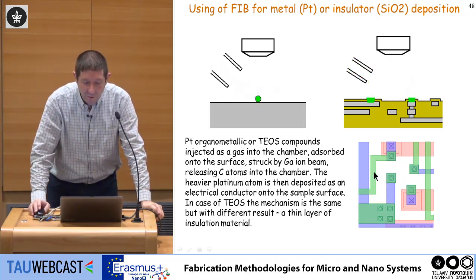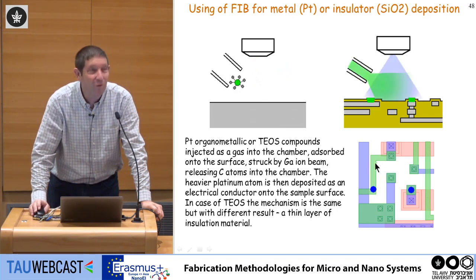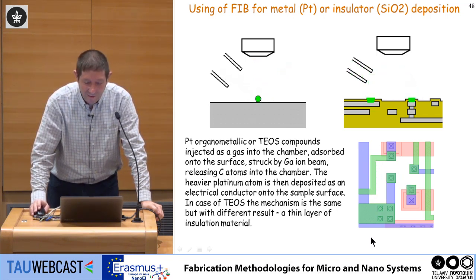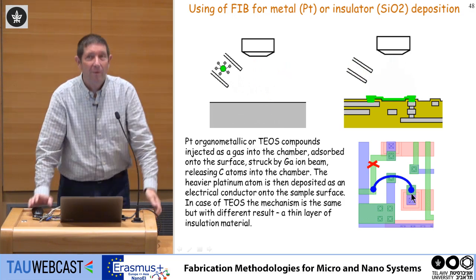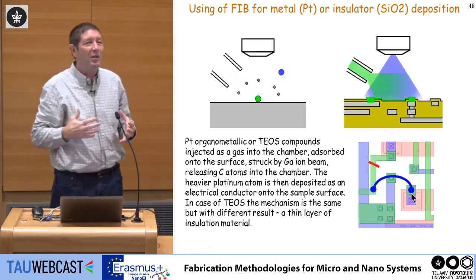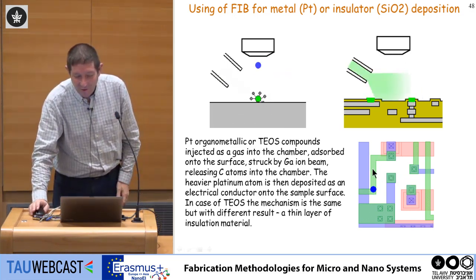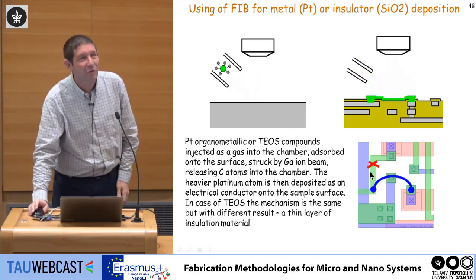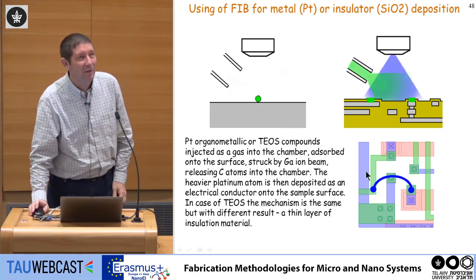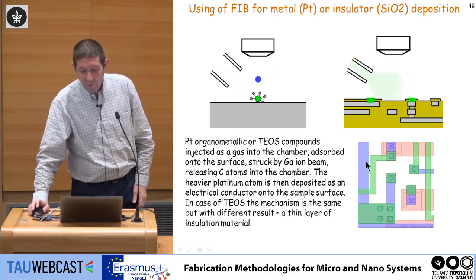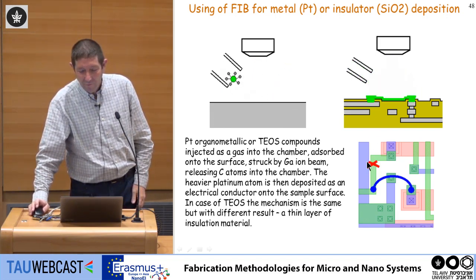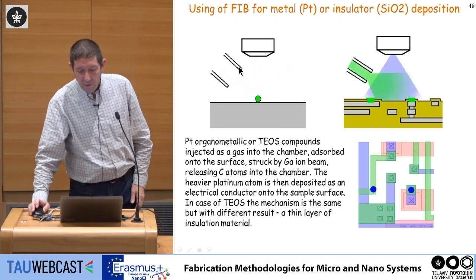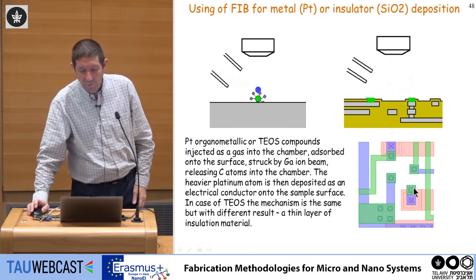So what happens? Let's say you can use the focused ion beam to cut this line. Let's say this is the layout of a cell. You want to cut this line here and connect this to here. You cannot do it with a regular probe station. You are talking about lines which are less than 50 nanometers. So you cannot do it manually. So what you can do is take the focused ion beam to cut this here. And then you can use the platinum deposition to make a short here.